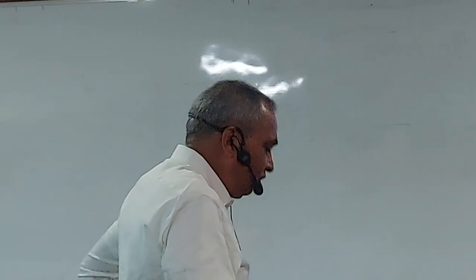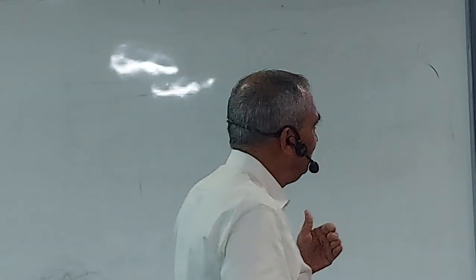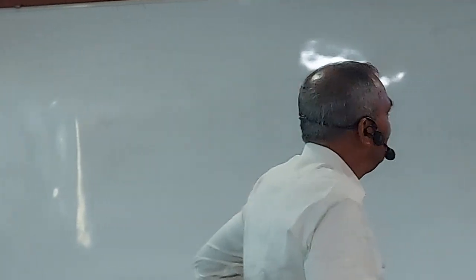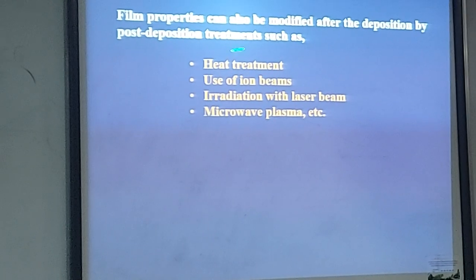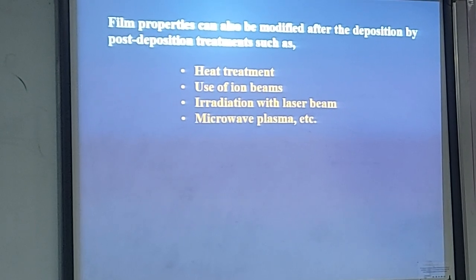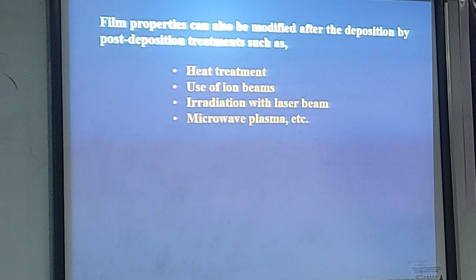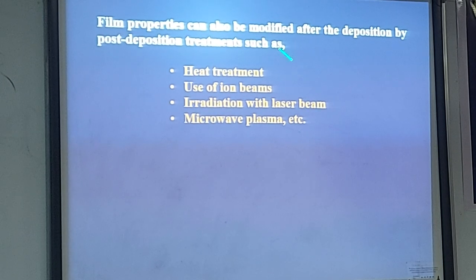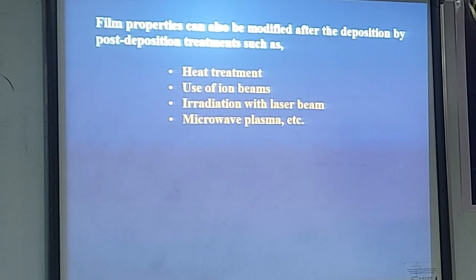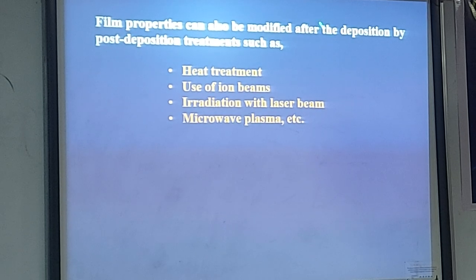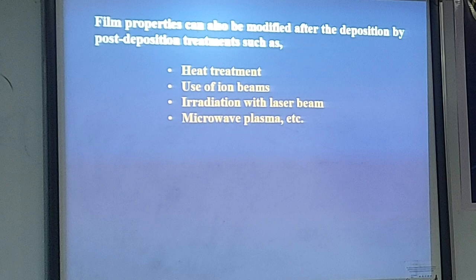And it is not only the condition that we maintain for the substrate during the growth process, but even after the deposition of the film, film properties can be modified by post-deposition treatment. It can be simple heat treatment. One can also irradiate with ion beams, which will modify the properties. Sometimes people irradiate with a laser beam. Also, it can be subjected to microwave plasma. These are all the possibilities by which we can modify the property of the film even after the growth, by a process called post-deposition treatment. I just wanted to highlight this because thin film technology is versatile,